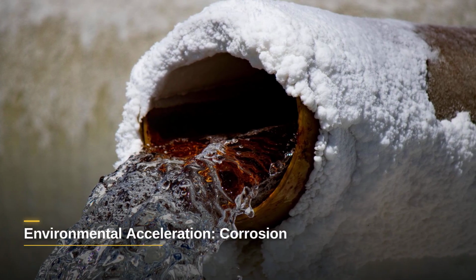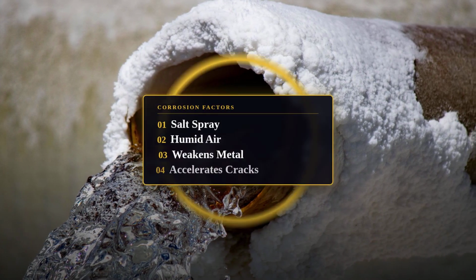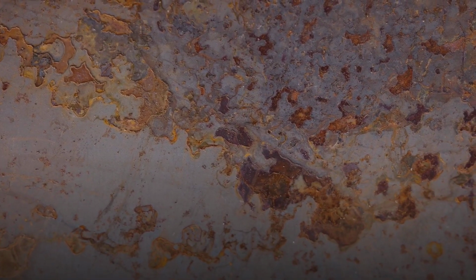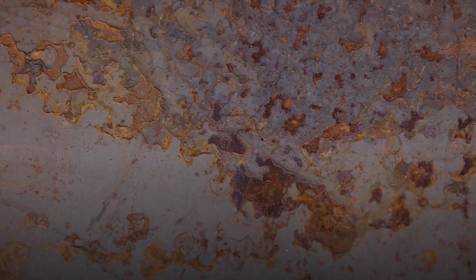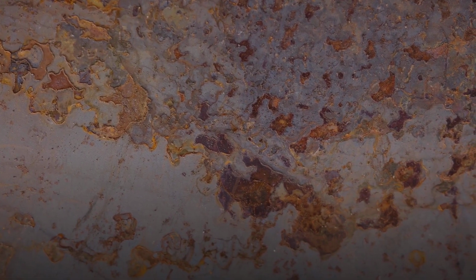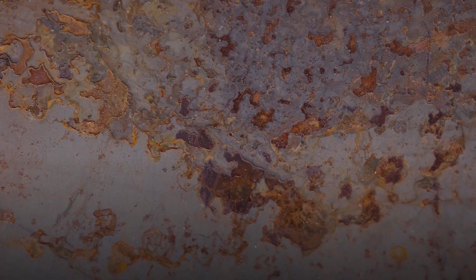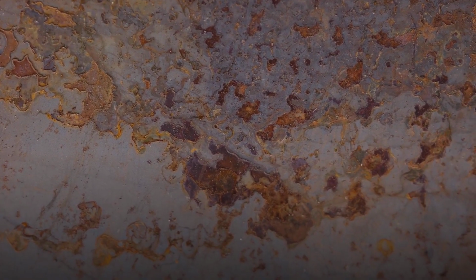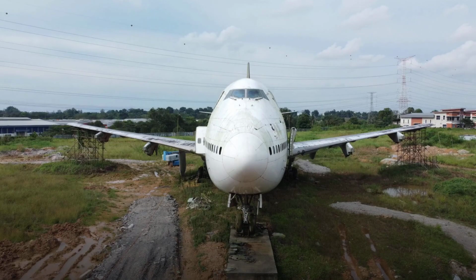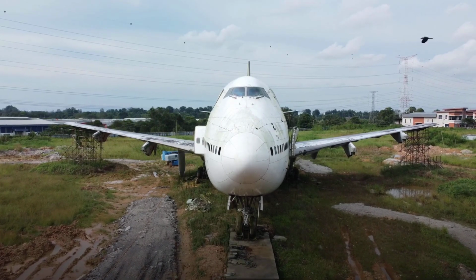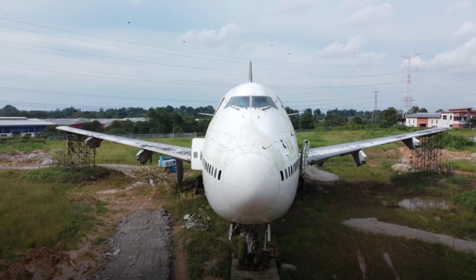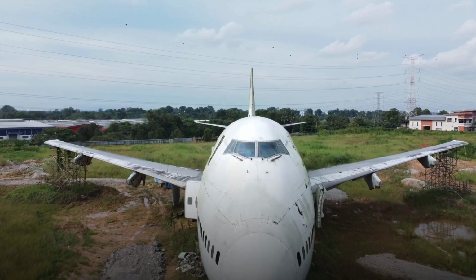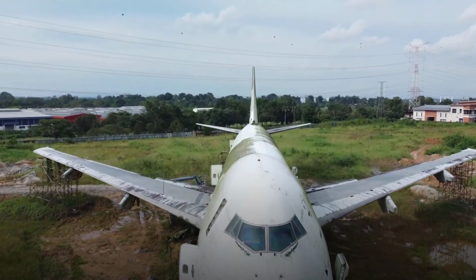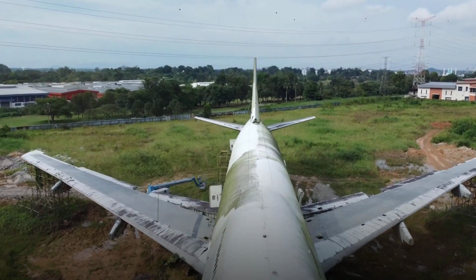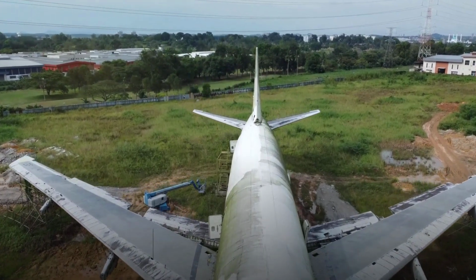Compounding the effects of cyclic loading was the corrosive environment of Hawaii. Constant exposure to salt spray and humid air accelerated the degradation of the fuselage's aluminum skin. Corrosion attacks the material, forming pits and weakening its surface. These corroded areas then become prime initiation sites for fatigue cracks. Once a crack forms in a corroded region, it propagates much faster than in pristine metal. For N73711, the tropical, marine environment acted as a silent accomplice, significantly accelerating the structural integrity's compromise.